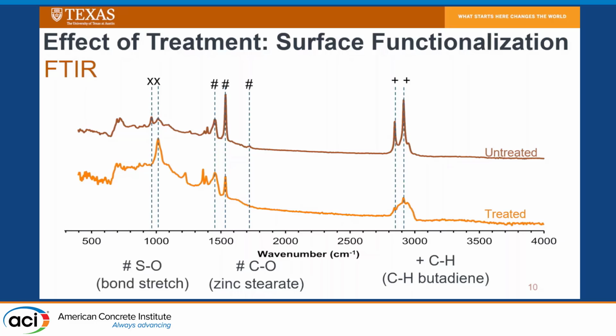And then this first peak over here is our sulfur-oxygen bonds. And essentially, we actually see this increase, right? So this increase corresponds to a bond stretch that is occurring over here, and this is due to the second step of the treatment process. So this is showing you that we actually are having this grafting onto our rubber particles.